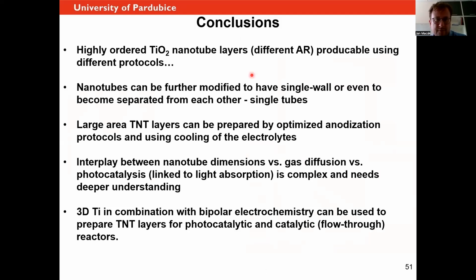Throughout different sections of my talk, I was hopefully able to convince you that we can grow nicely ordered nanotube layers of different aspect ratios using different protocols, which are also reproducible because many people use it. These tubes, they are always double wall, especially in ethylene glycol, and they can be etched to have single wall, or even they can be etched to single tube powders. We can play also with the anodization protocols to make really large area nanotube layers. And obviously there's some interplay between the nanotube dimensions and the photocatalysis. And we haven't reached yet the saturation, but we think that the thicker layers, the better.